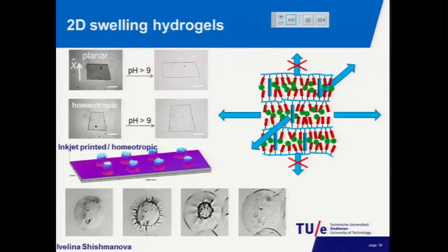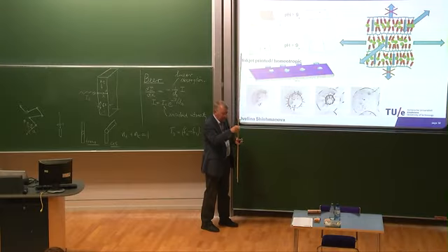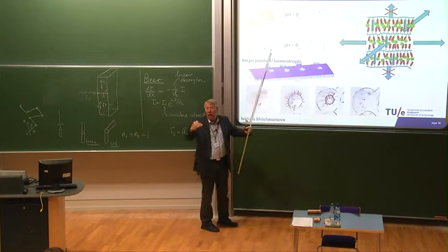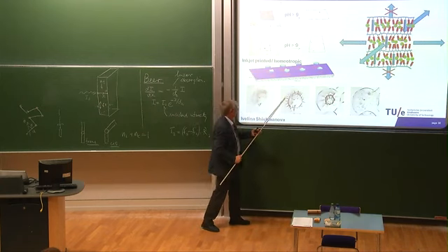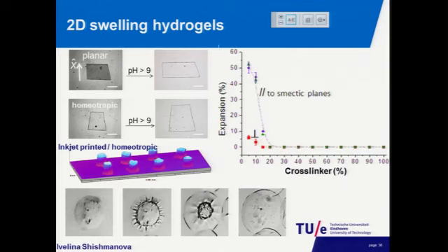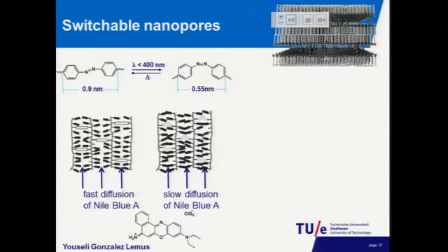In this case, the orientation is homeotropic, so the layers are in the plane, so material swelling should occur from outside inwards, which can be seen here as well. And this is a measurement showing the large anisotropy in swelling. And we are utilizing these systems now to make water deforming systems, triggered systems that respond to the presence of moisture in this case. And this is my almost last slide.